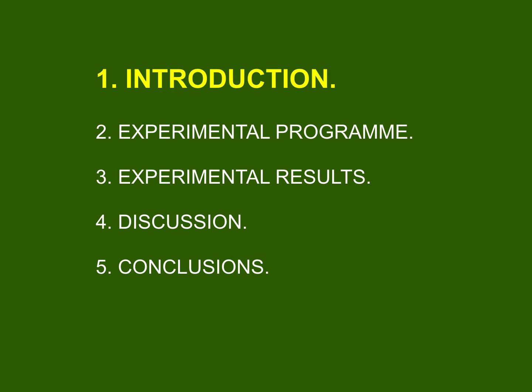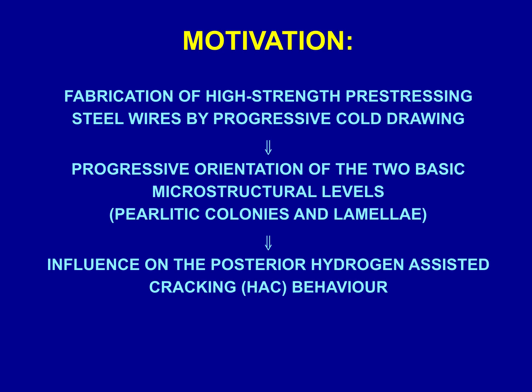First of all, the introduction. The motivation: fabrication of high-strength pearlitic steel wires by progressive cold drawing produces a progressive orientation of the 2 basic microstructural levels of pearlitic colonies and lamella, and as a consequence, an influence on the posterior hydrogen-assisted cracking behavior.